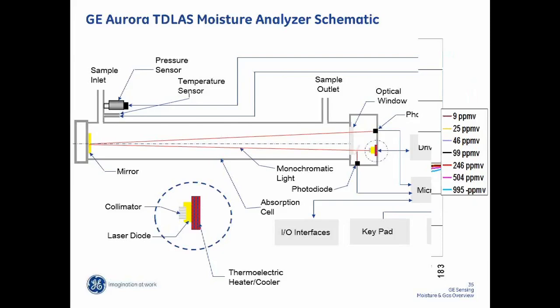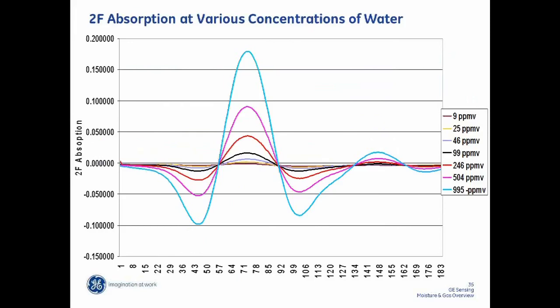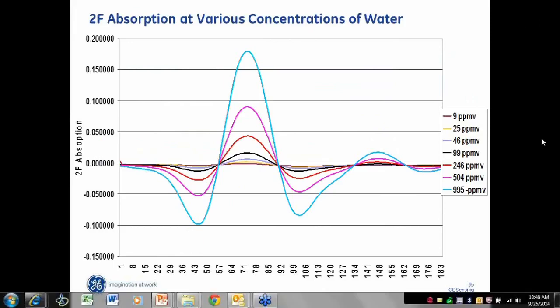This graph just shows the absorption peak at various concentrations, and so we can see that there's a direct proportionality to the height of the peak, centered right around 71 on this graph, and the concentration in parts per million. And this is what's called a 2F or raw signal. So when we calibrate these systems, we're recording that peak height versus the concentration and using that as a lookup table for the system. So one nice thing about this system is it's very, very repeatable.